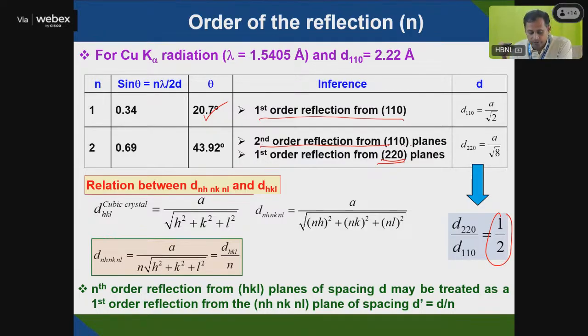That means if nth order, it will take dHKL and d(nh, nk, nl) will be dHKL divided by n. So n is your order of plane, like you take the fifth order plane. So for the fifth order plane, the d value will be whatever the dHKL of the first order plane is, divided by 5. That means nth order reflection from an HKL plane of spacing d may be treated as a first order reflection from the (nh, nk, nl) plane with d spacing d dash equal to d by n. That means the second order plane of 110 will be the first order plane of 220. Similarly, if you go to third order, fourth order, they will change accordingly. So you will get a relation d(nh nk nl) equals dHKL divided by n.